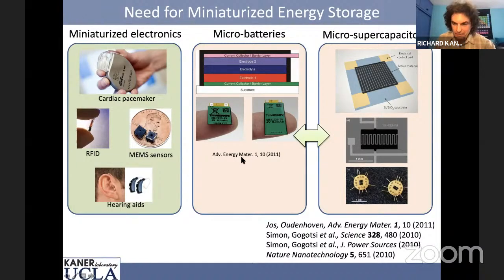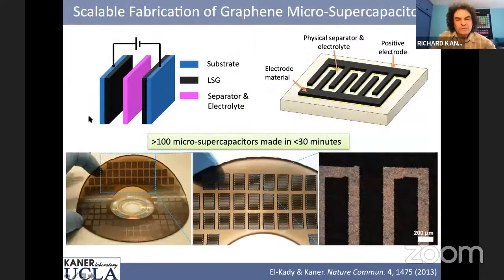And so here's some designs for interdigitated electrodes, and you'll see our host, Yuri Gogotsi, did some early work on making some of these designs. And so we simply borrowed some of his designs, and we can produce this with laser scribe graphene. So again, we take a piece of plastic, we coat it with graphene oxide, and in this case, we tell our laser computer program to go and make over 100 micro supercapacitors. And these supercapacitors have this interdigitated design.